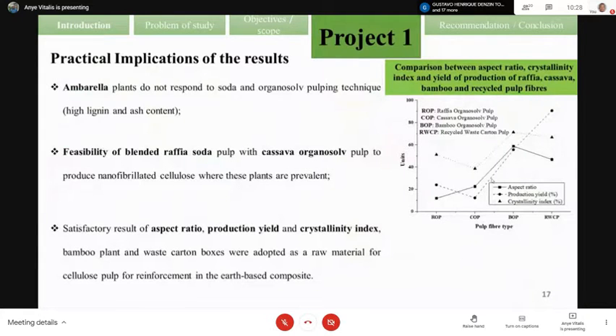What is the practical implication of this result? We show that by using Ambarella fiber, we cannot achieve a pulp or nanofibrillated cellulose due to the high amount of lignin and ash content. Also, there is feasibility to use raffia and cassava for nanofibrillated pulping, but economically it doesn't have a good implication due to the low yield of production.